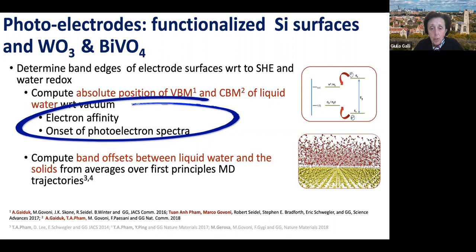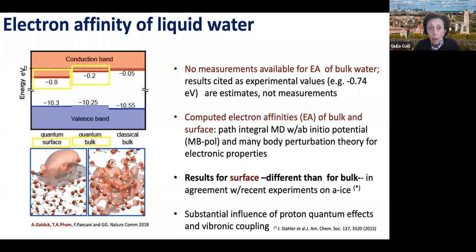And every time that I quote people and references down here, I try to highlight in red all the junior people that contributed to all of our papers. So we computed the electron affinity of water. We computed photoelectron spectra, and the onset tells you the position of the valence band. This has been quite a task to compute these two quantities, and let me tell you what we have learned. So this is a work that we have done in collaboration with Francesco Paesani, and we ended up computing the electron affinity of water, not just by doing a straightforward first principle MD, but using the potential that Francesco has developed, which is called MB-pol, and doing simulation also with path integral.